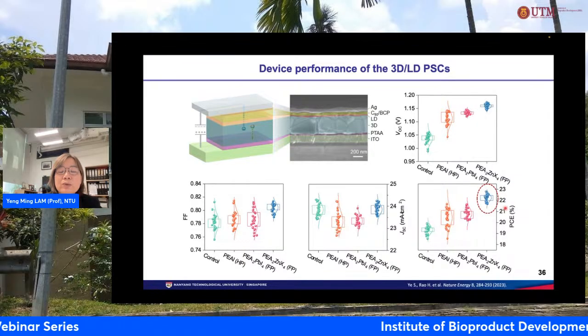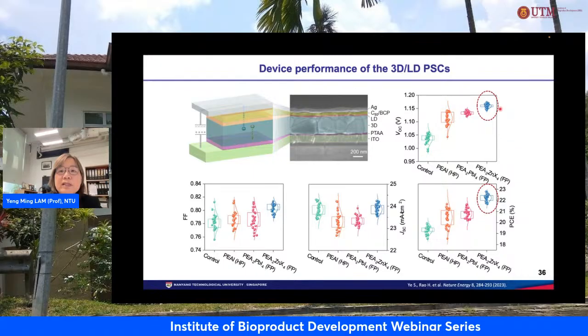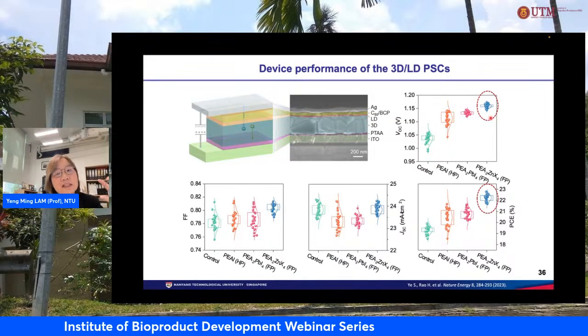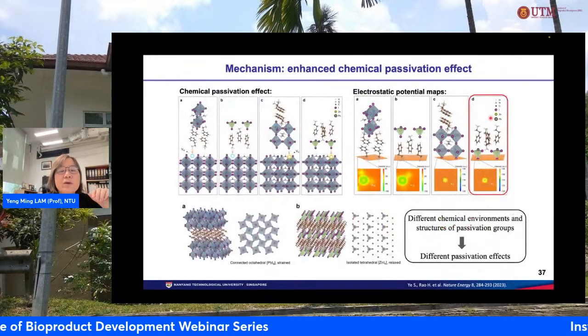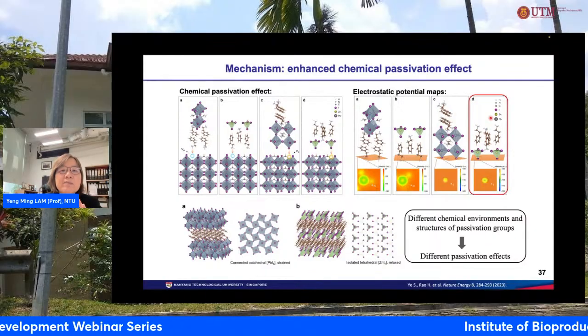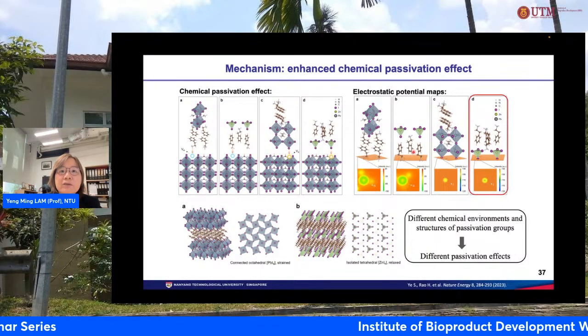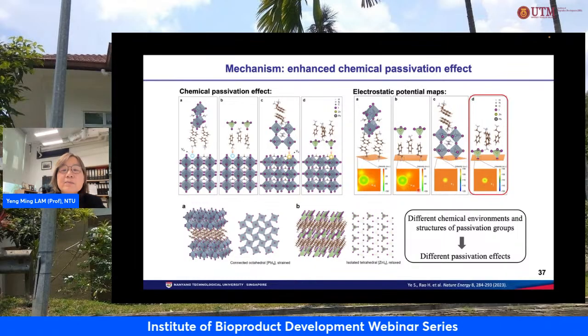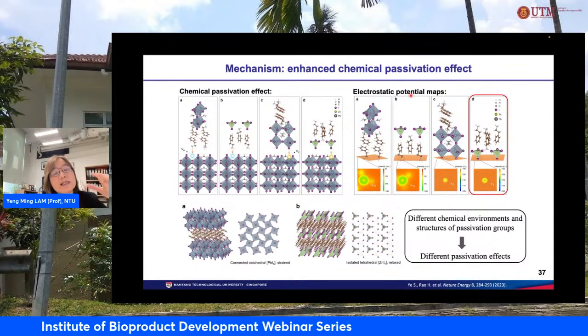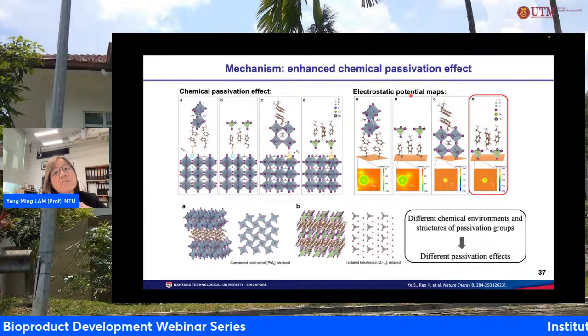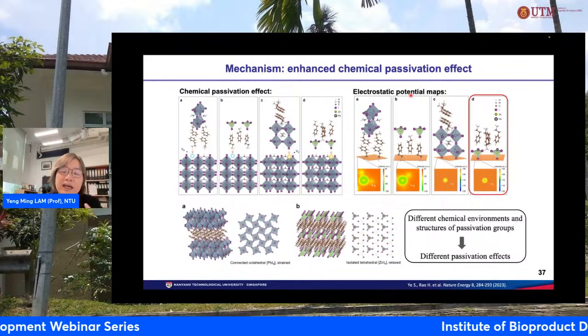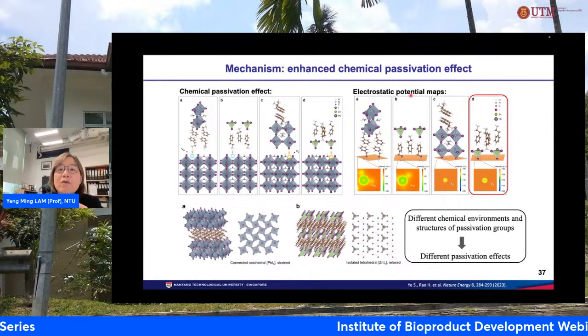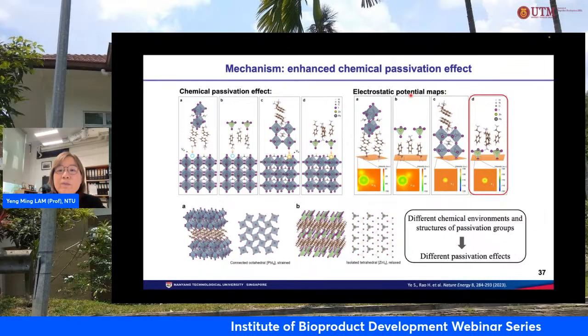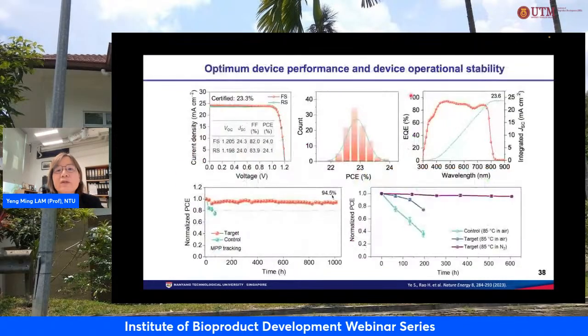It's actually 23% maximum. The reason is because our open circuit voltage is very high, so the interface now improves. I will skip this, but just as a summary, the reason for this enhancement in our efficiency is because the electrostatic potential is better matching with the new material, where I can now put in different types of organic cation to form this low dimensional material.